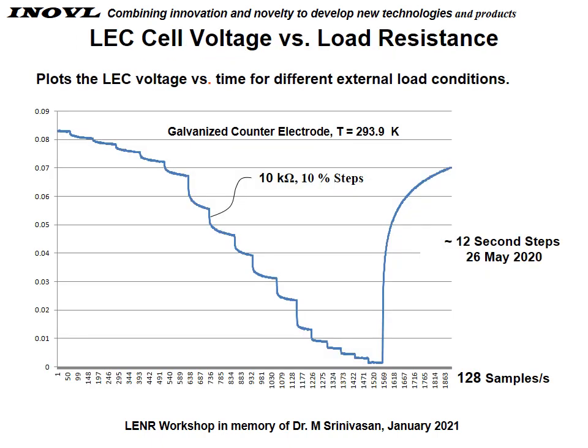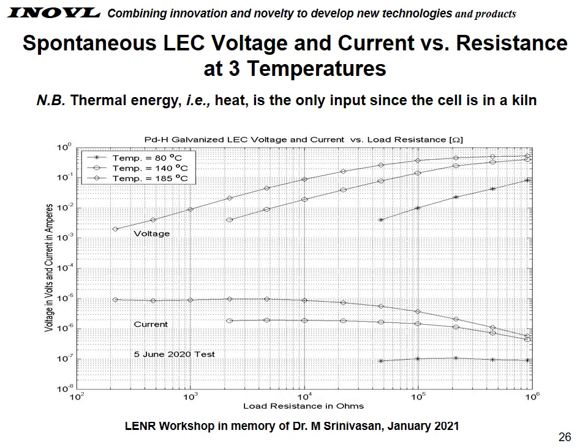This slide shows a typical test to characterize the LEC. In this case, we're measuring cell voltage versus load resistance across time. We had a resistor box, and by changing the resistance values, we could change the load on the LEC. And as we changed the load, we could watch the current come down. And as you can see here, we started at about 1 megohm, and we ended at probably less than 50 ohms across the cell. Then we went back to 1 megohm, and the voltage went back to the previous example.